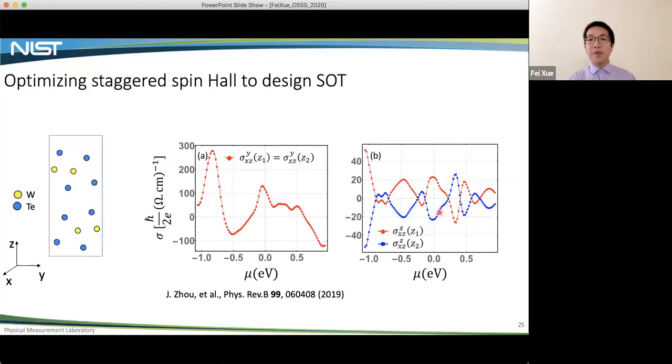Yeah, so in the experiment, they also have multilayers, and they don't see an increase of the output torque, so this staggering also qualitatively explains why. Because staggered does not add up like the uniform one. Even if I do 3, 4, 5, 6 layers, they always just alternate the sign rather than increase their magnitude. And I expect there may be a very short spin diffusion length.